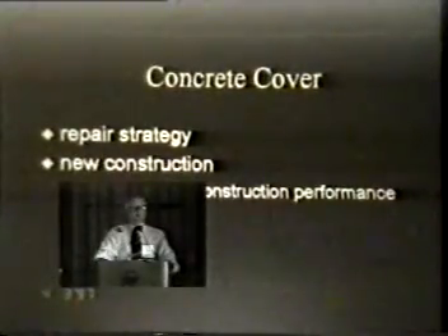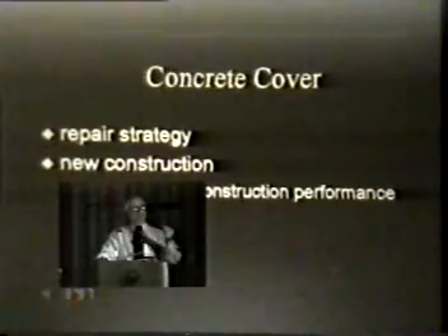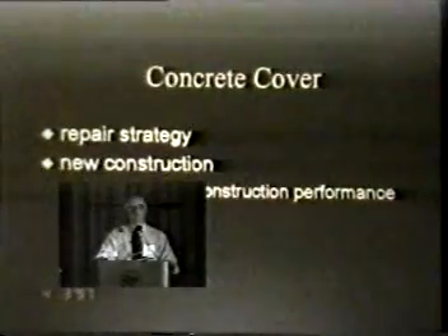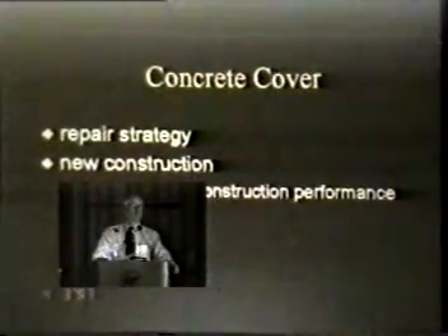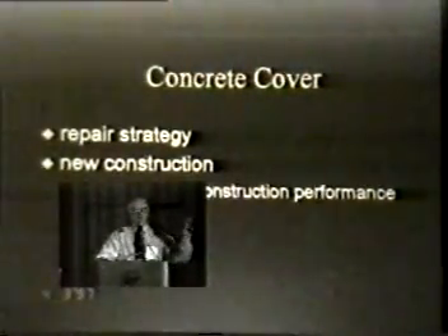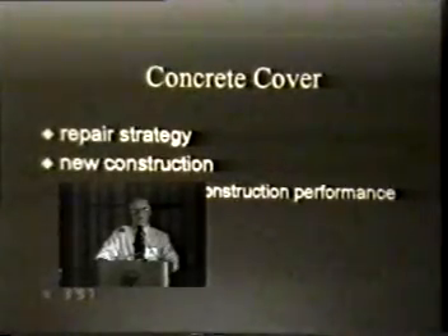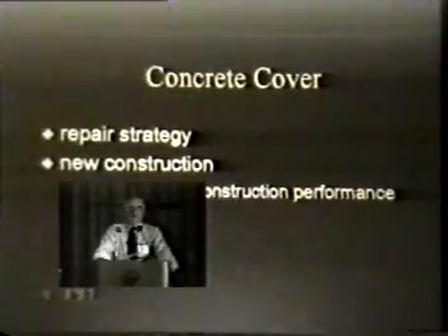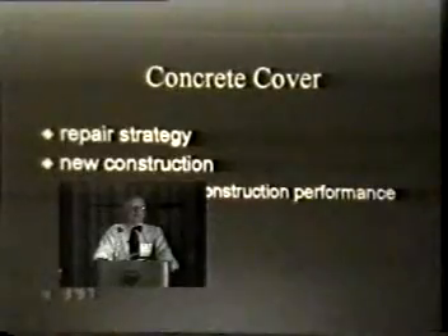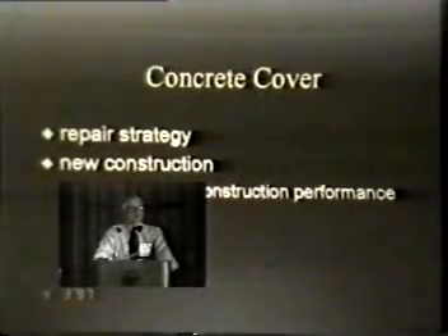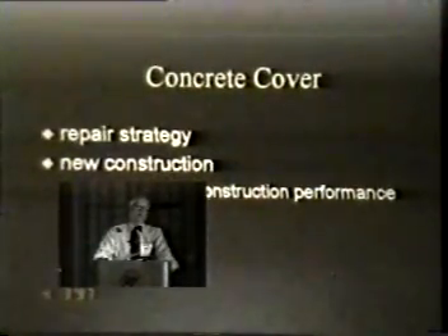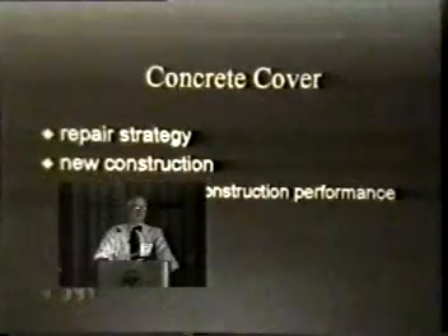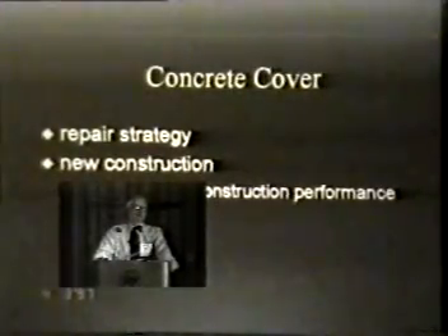So they mapped it out, and they found 450 locations where the bars were too close to the surface, from 0 to less than 1 inch. The specs called for 2 inches. So they came back to the contractor and said, what are you going to do about it? This is a big problem. Here you've got a brand new structure. This is one of those unusual owners that found out he had a problem right when it was being built. So what do you do about it?